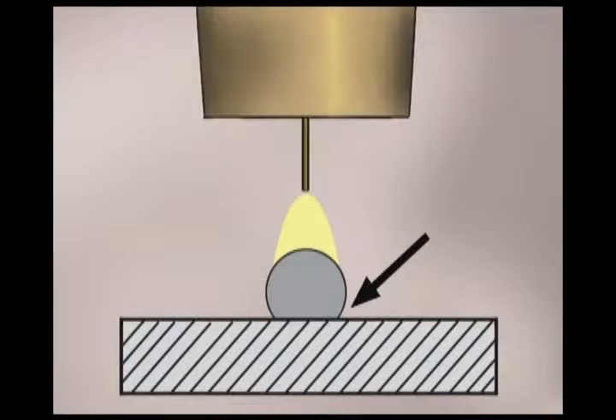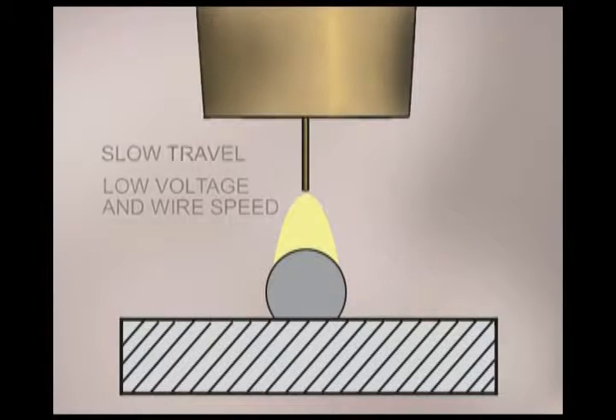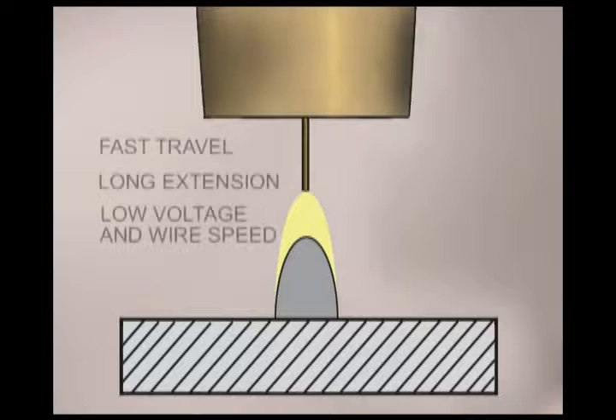If the edges are rolled over, your travel speed may be too slow, along with too low of a voltage and wire speed setting. If the weld bead stacks up, not flowing out on the sides, you might be traveling too fast, using too long of an electrode extension, or the voltage and wire speed are set too low.